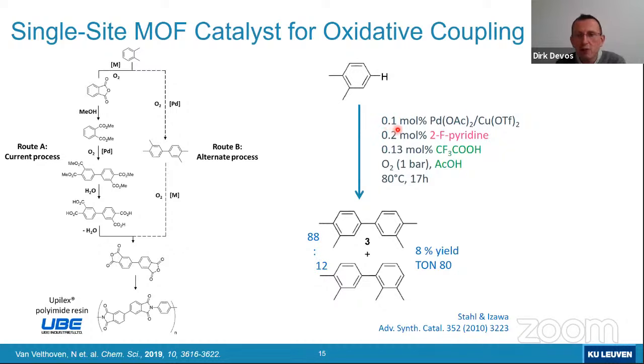It has been shown that by choosing the right combination of palladium and copper, and then by also using some very specific ligands like this fluoropyridine and working with even trifluoroacetic acid, which is maybe not the most desired molecule, you can still achieve quite good selectivities for this desired isomer of the bis-xylyl, and the turnover number is also quite significant. Now, this is still a di-substituted molecule, and you can imagine that it is much easier to reach a higher selectivity with this di-substituted molecule than it would be with simply toluene. But anyway, the challenge already is to reach a sufficient activity also with this type of coupling reaction. Even notwithstanding the selectivity, activity is already quite important, and even recovering the palladium is a challenge that we really need to meet.